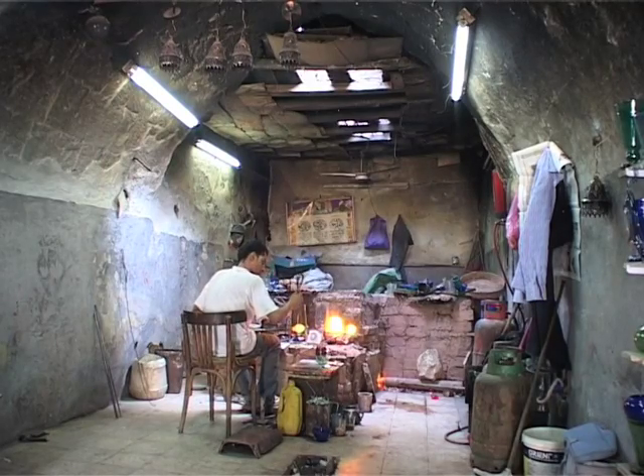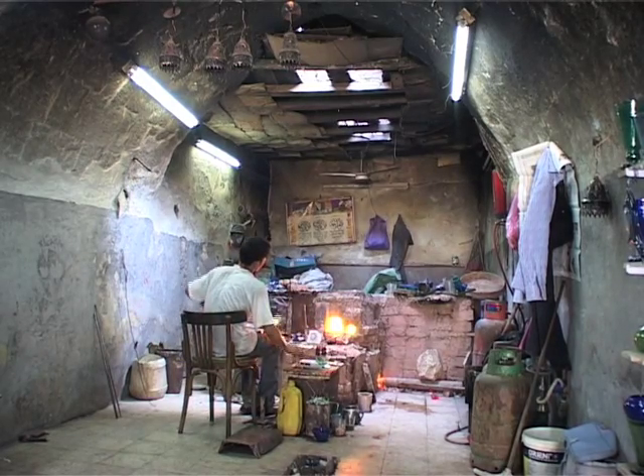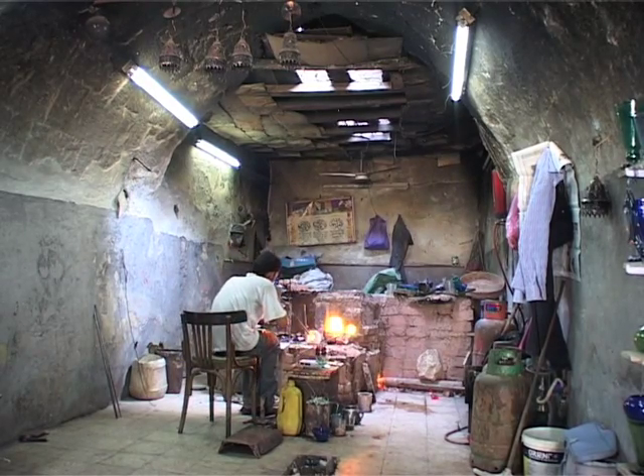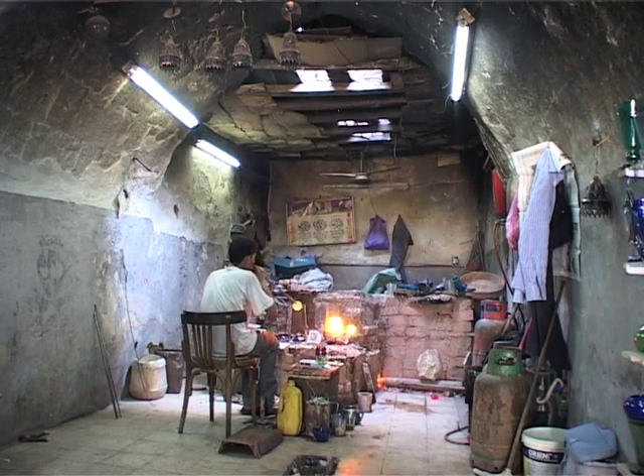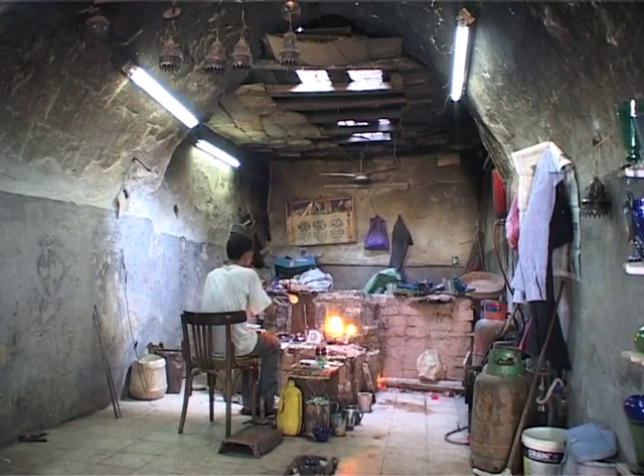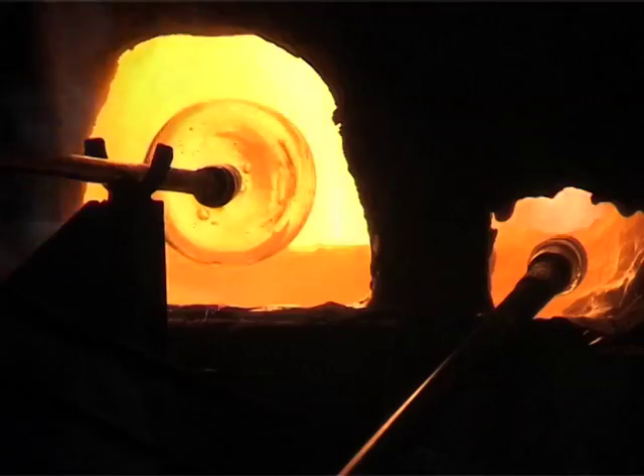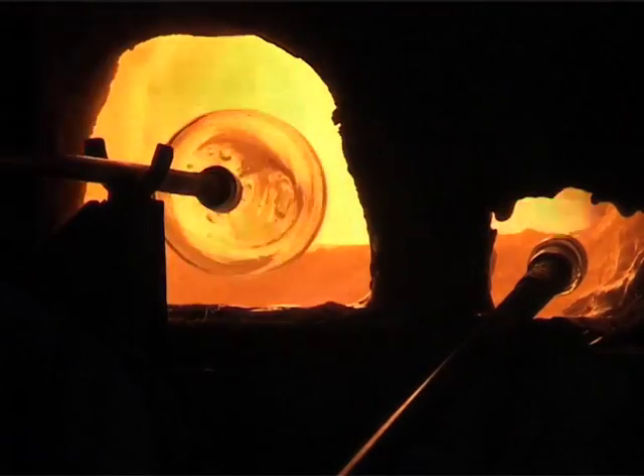Comparing the weight of the slab with that of the finished objects shows just to what extent with these furnaces we are dealing with an industrial production. A slab of 20 tons could produce nearly 80,000 bottles, or 1,500,000 little flasks, or even 275,000 bowls.